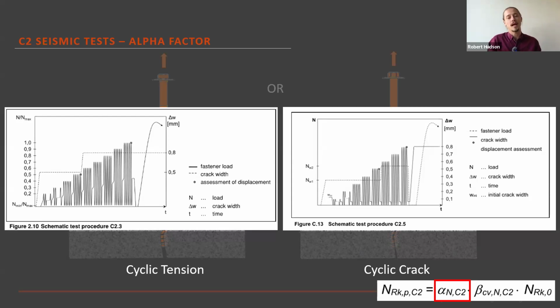Now, when we were doing this testing, we started playing around in our own lab with some of the variables. We wanted to understand what the sensitivity of these variables were, because you'd get some test programs where your variable is set as a number and you could increase it and decrease it, and it's not that sensitive and doesn't really have a big impact on the outcome. So we wanted to understand how sensitive these variables were to the end result we were getting. And so we played around with it a little bit, and the conclusion was they're incredibly sensitive. And the two variables that we care about here are the crack width, so that 0.8 mm, and the number of cycles that we're putting the crack cycle test through.